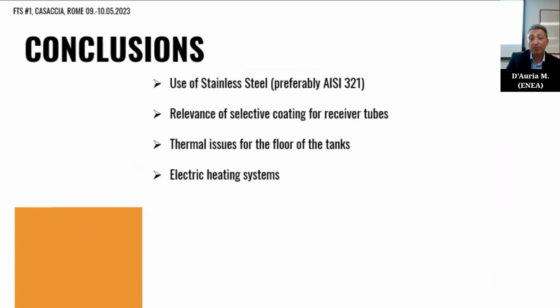So to sum up, the use of molten salts requires certain precautions, especially if we want to exploit the full working temperature range, and above all, avoid the risk of freezing. For pipes, vessels, tanks, but also pumps and other components, it is recommended to use stainless steel AISI 321.